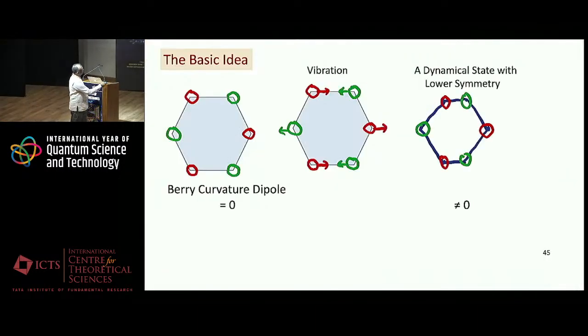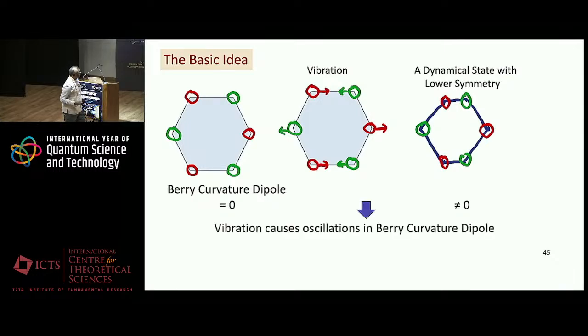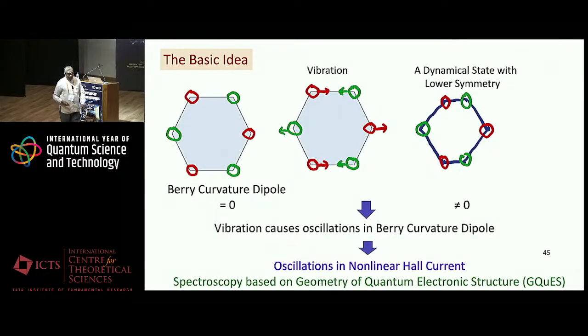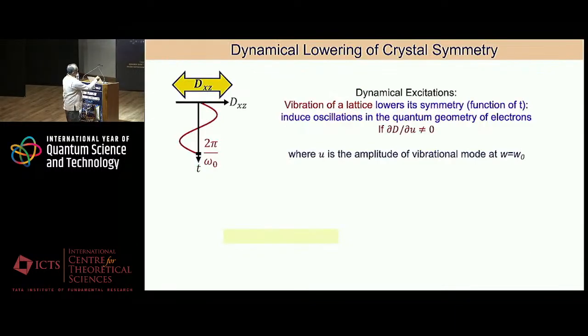So you have a basic idea here that you have this graphene-like system or any lattice. Vibration will lower its symmetry dynamically, and this dynamically lowered state can have a non-zero Berry curvature dipole, and vibration can create oscillations in the Berry curvature dipole, and hence the nonlinear Hall effect. And based on that, we propose the spectroscopy called geometry of quantum electronic structure based spectroscopy. So the idea is this: you have this Berry curvature dipole as a function of time.